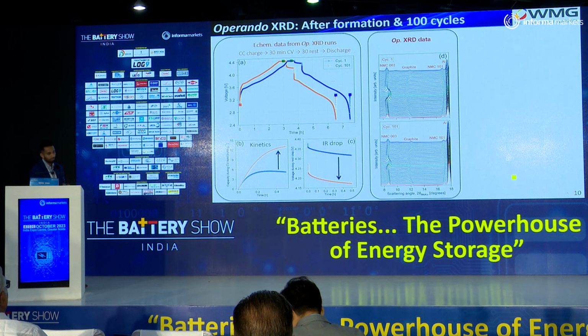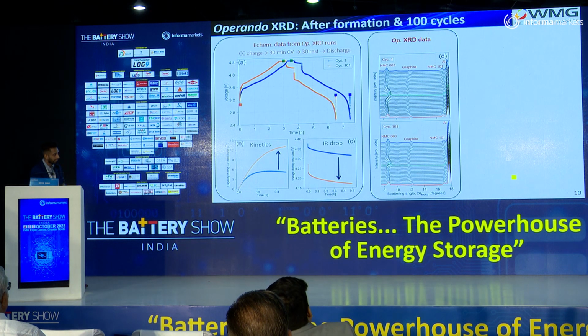So, what do these graphs actually mean? Well, our cathode material is somewhat like an elastic band. As you charge up, that elastic band expands. And as you discharge your material, the elastic band contracts again. So we start from the top, we expand to the peak of charge, and then we contract to the bottom of charge. And what does this actually tell us? Well, it tells us how our material is allowing lithium to come in and out of our cathode. And this is very important for things like fast rate capabilities and understanding material degradation.